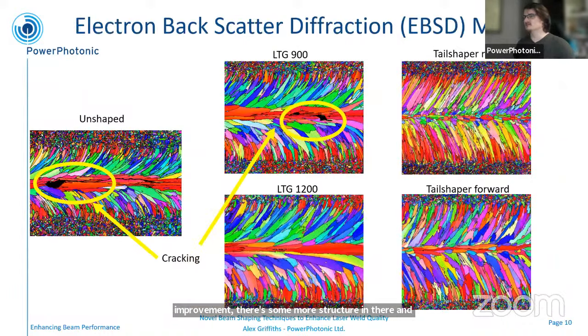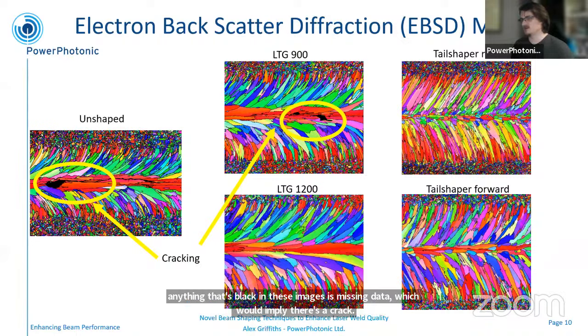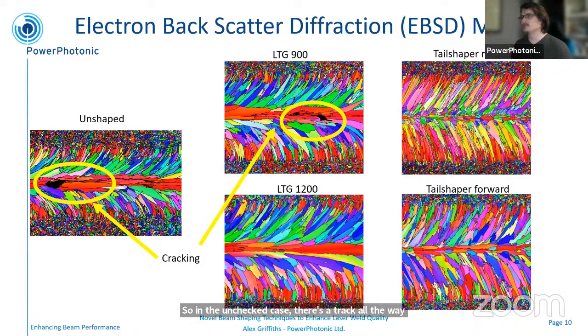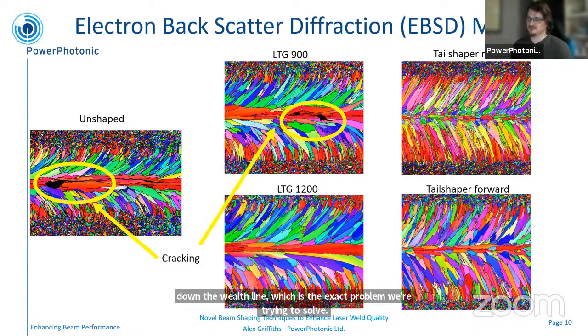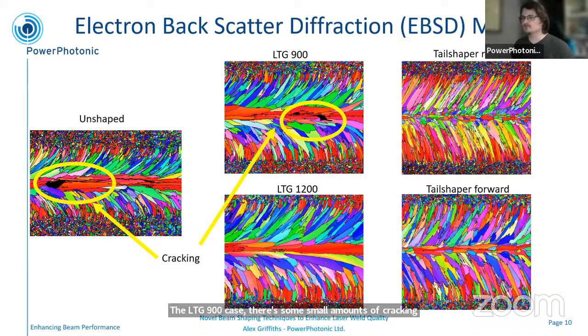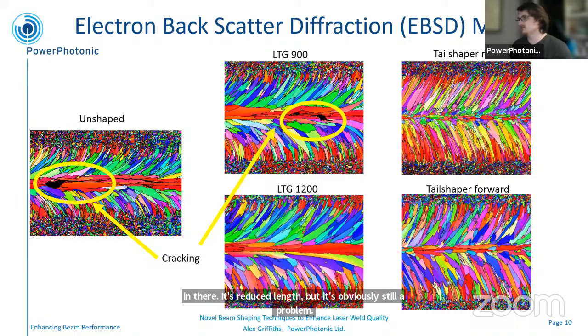To make that a bit more quantitative, we have also done electron backscatter diffraction measurements. This is to show the actual grain size in the welds. Immediately, the obvious thing to spot is anything that's black in these images is missing data, which would imply there's a crack. So in the unshaped case, there's a crack all the way down the weld line, which is the exact problem we're trying to solve. The LTG 900 case, there's some small amounts of cracking in there. It's reduced length, but obviously still a problem. Not seen that in the 1200. We're not seeing that in the tail shaper in either orientation.